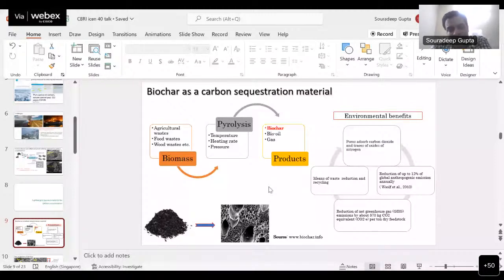There are several life cycle analysis studies that have been done on this. For example, Woolf et al., 2010 has reported that about 12% of global anthropogenic emission can be reduced by using biochar as a soil enhancer and a filtration material. Similarly, there are other reports showing that about 870 kg CO2 equivalent per ton of the feedstock, that is the parent biomass, can be captured by using biochar as a building and filtration material. So besides being a solid waste management strategy, it can also reduce the associated carbon emission, because we are capturing the carbon in the structure of biochar instead of turning it into ash and emitting the carbon to the environment.